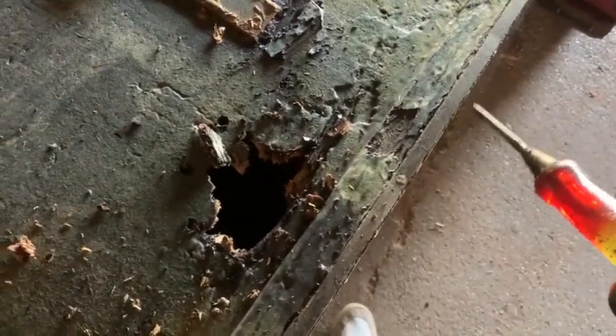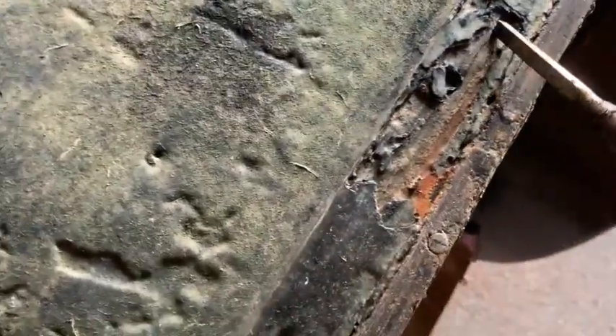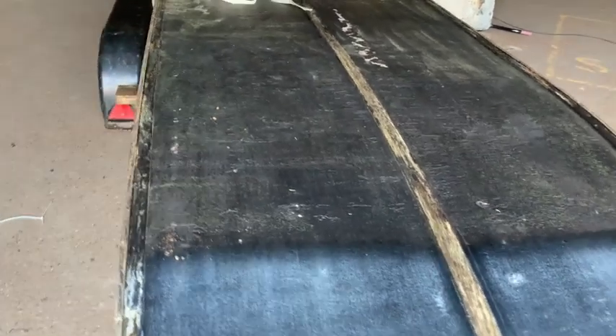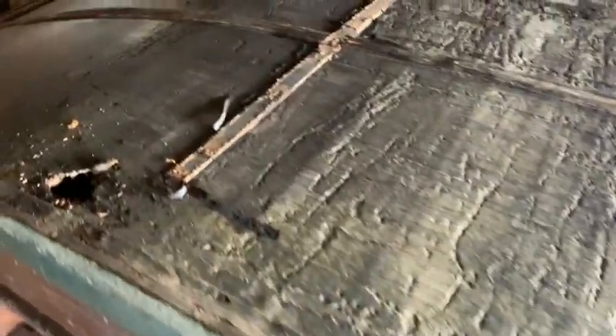The softwood was in a nice condition on the last one I showed you here. You can see that it's become misshapen and it's been worn away, kind of like driftwood. So I think that in this scenario, with plywood being used on the bottom of the boat, then absolutely epoxy is superior to your traditional bitumen.